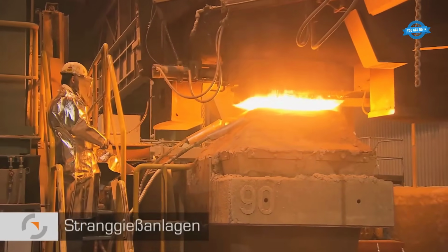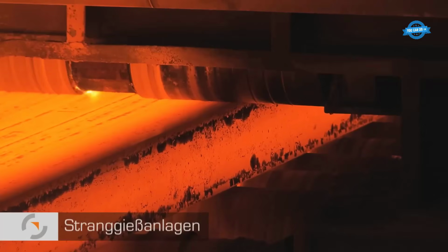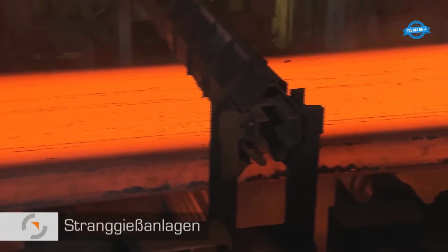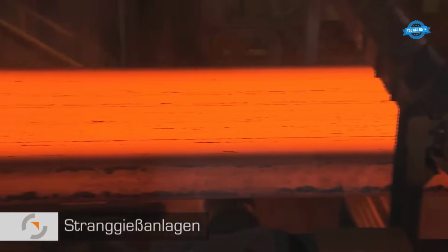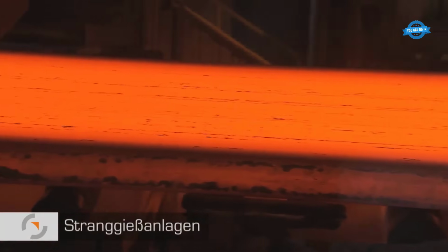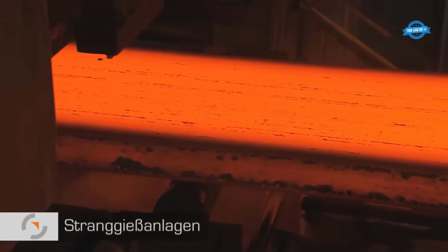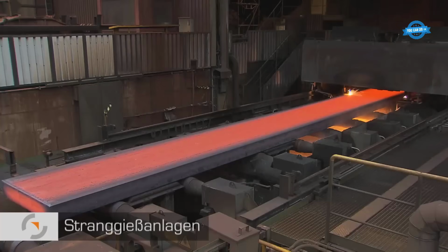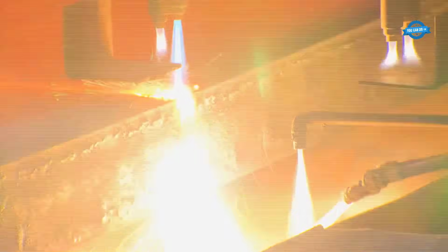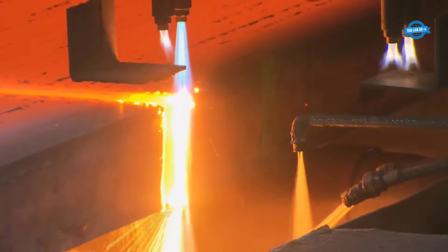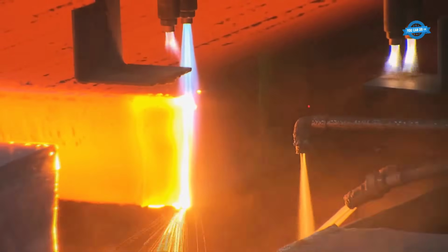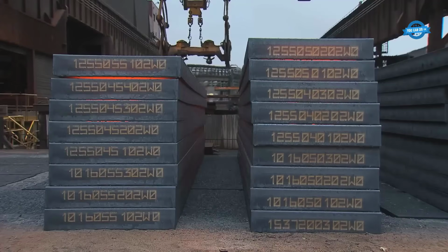These distinct steel grades are then directed to continuous casting lines that fashion them into slabs from the molten steel. These slabs develop a solid outer shell while the core remains molten. The slabs are subsequently torch cut into manageable pieces for shipment. These slabs, some as thick as 35 centimeters and weighing up to 32 tons.